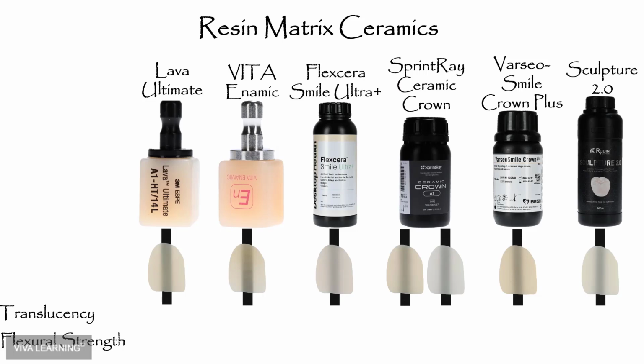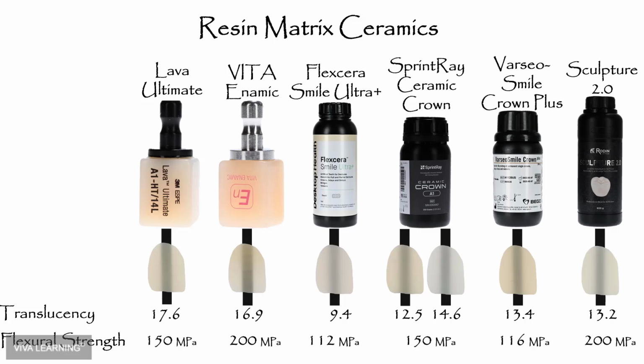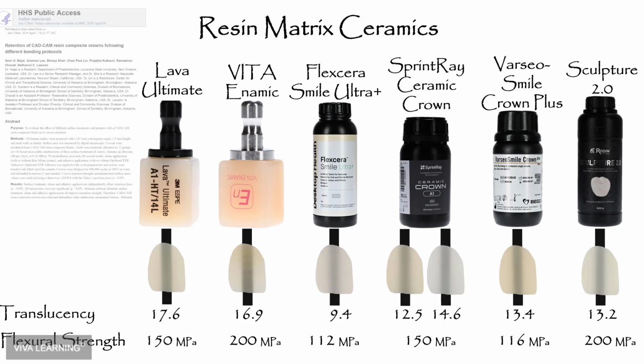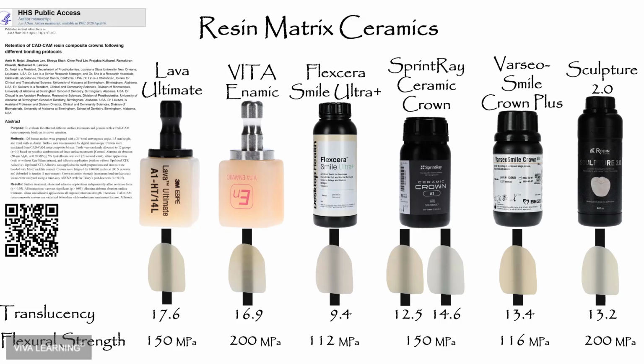And when we look at the different materials we have available, we can see that they have an acceptable translucency and a relatively low flexural strength. And we need to remember that one of the main challenges with Lava Ultimate was its debonding. We did a study back then and found that it is very crucial we do bond these restorations in place rather than just luting them.